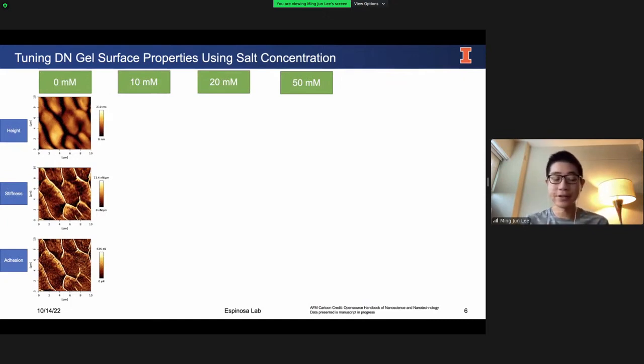I'd like to direct your attention to the first diagram on the top, the upper left. And we see a very unique microstructure for my double network hydrogel. It looks sort of like a grain structure, or even like bubble wrap that we have in our shipping containers. The elevated orange grains, I believe, are the copolymer component. So that's the acrylamide-co-acrylic acid component, whereas the black areas that are lower in height, the valleys, I believe are